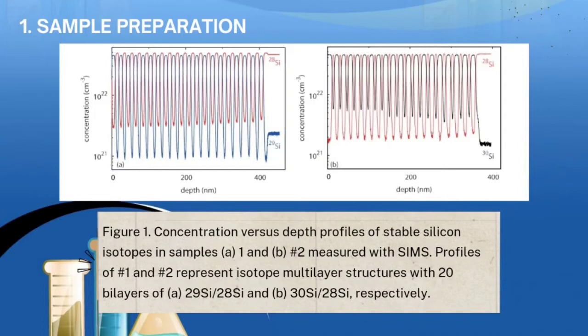Undoped bilayer structures of 29 silicon per 28 silicon is sample 1, and 30 silicon per 28 silicon is sample 2. They were grown by MBE on p-type substrates, boron doped, with a specific resistivity of 0.02 to 4 ohm centimeter. The thickness of each individual isotope layer is about 10 nanometer, resulting in a total thickness of about 400 nanometer for the entire layer structure. This figure illustrates the concentration of the silicon isotopes versus depth of sample 1 and 2 respectively.